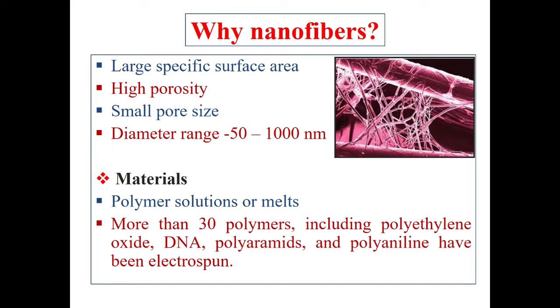Nanofibers have large specific surface area, high porosity, small pore size, and diameter in the range between 50 to 1000 nanometers. The length is in the millimeter or micron size, but whatever the diameter associated with that particular fiber, that diameter should be in the range of nanometers, then that fiber is called a nanofiber. Various materials can be used, and their fiber can be drawn easily with the help of different techniques.